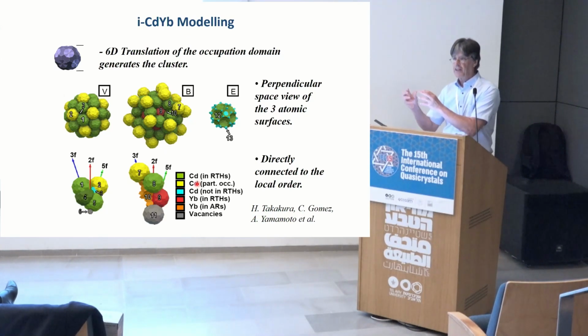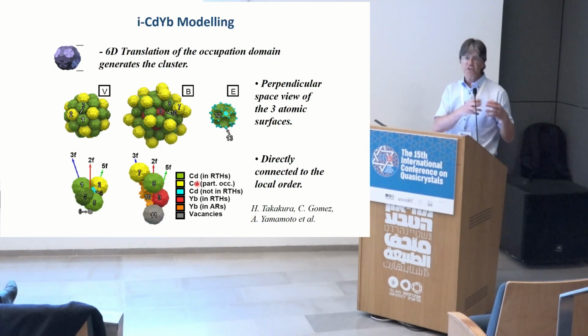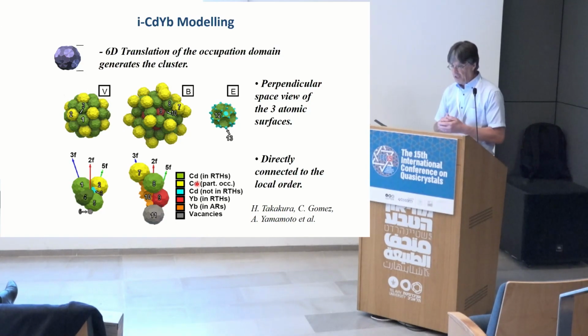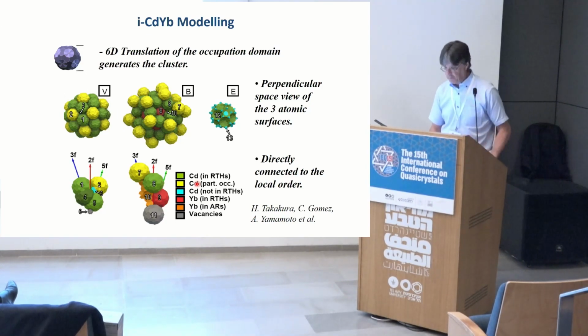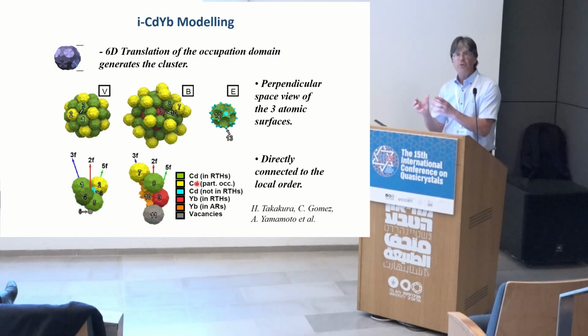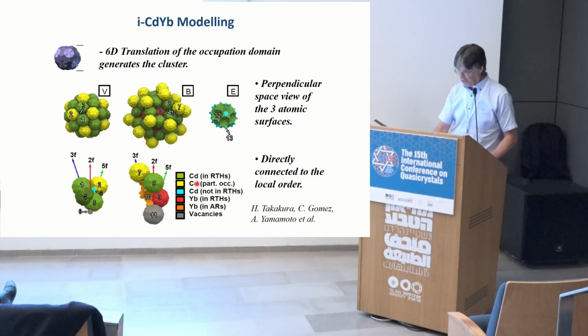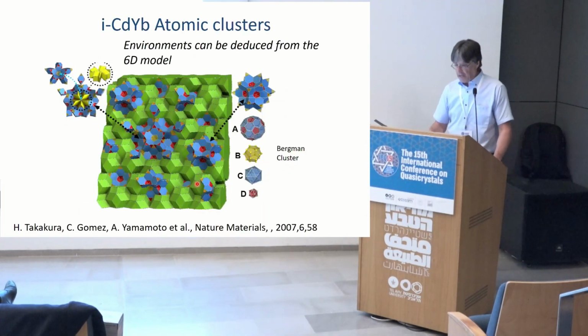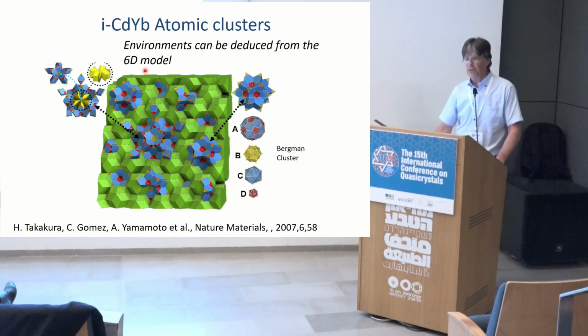We had the synchrotron data. We had the tools for deriving the structure, developed essentially by Akiji Yamamoto for this specific case. We had this binary crystal, so all the puzzle could be solved. And I think it's better to go directly to real space. So that's the distribution of clusters that you could derive from this high-dimensional crystal. The environment can be deduced from the 6D model.